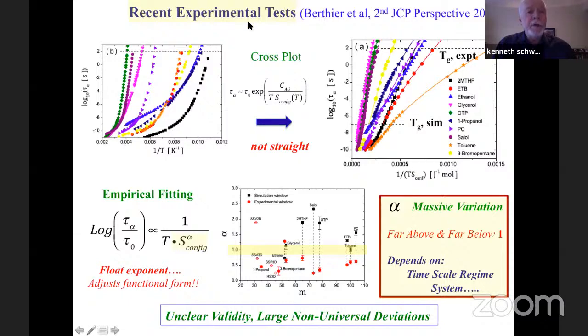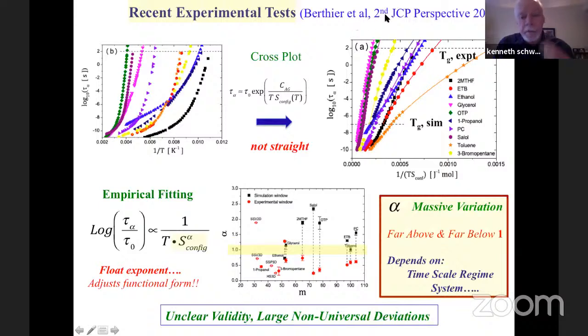So again, I'm not an expert in this area, but I read this interesting second perspective of Berthier et al. that tried to evaluate the configurational entropy idea. And so here's one snippet from this paper. So here's a bunch of experimental data over 13 orders of magnitude, alpha time versus inverse temperature. So if this formula was correct, then if you plotted the log of this versus 1/T times configurational entropy, the data should be straight. Well, at least for these of the order of 10 systems, the data is not really straight. In fact, you can look at the data on time scales that you can probe on the computer.